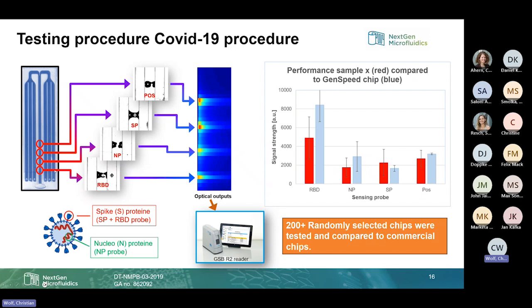So that was already shown by Max. Typically you have, this is the sensing channel. That's the same as with the injection molded chip on the roll-to-roll chip. And you have these 4 sensing areas where you detect: 3 of them are for the antigen proteins of the virus, and 1 is a positive control. And then via a chemo-luminescent reaction, you get 4 distinctive light signals, which can then be directly compared between the chips to test their performance.